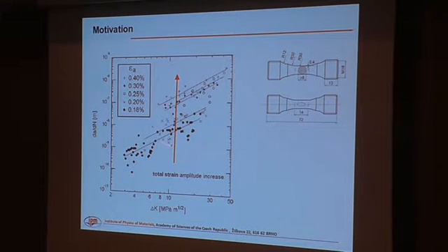These are our results which we obtained in the measurement of Eurofer steel, where we were trying to estimate the fatigue crack growth rate of really small cracks. The experiment was done on this type of specimen, where there was a small shallow notch in the middle, and the fatigue crack growth rate was measured using a long distance microscope.